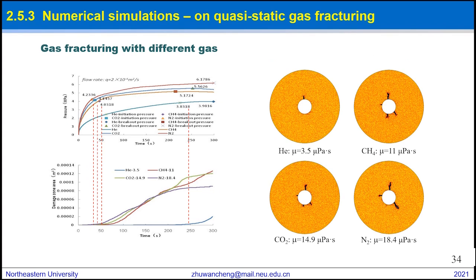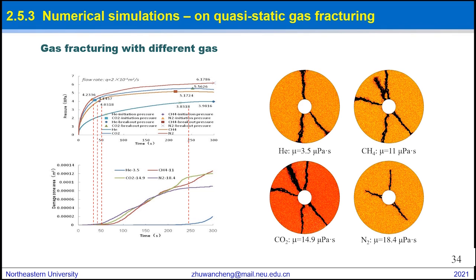In this slide, the impacts of different fracturing fluids on fracturing initiation pressure, breakdown pressure, and damage zone area are numerically examined. The initiation pressure and breakdown pressure are in descending order for nitrogen, carbon dioxide, methane, and helium, respectively, indicating that a low viscosity fluid like helium can lead to a lower breakdown pressure. Also, the damage zone area of helium fracturing is significantly smaller than that of fracturing by other fluids. In addition, using carbon dioxide and nitrogen as the fracturing fluid, multiple irregular cracks are induced more easily than with methane and helium. The fracture surface morphology induced by gas fracturing with carbon dioxide and nitrogen is rougher and more complex than that by methane and helium fracturing.